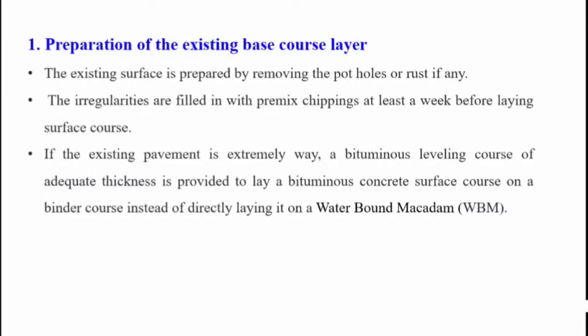The first step is preparation of the existing base course layer. Bituminous concrete is usually provided as a wearing coat on an existing base. The existing surface is prepared by removing potholes or ruts if any. If the surface contains irregularities, it is filled with premix chipping at least a week before laying. If the existing pavement is extremely weak, a bituminous leveling course of adequate thickness is provided as a binder course instead of laying directly on the water-bound base course.